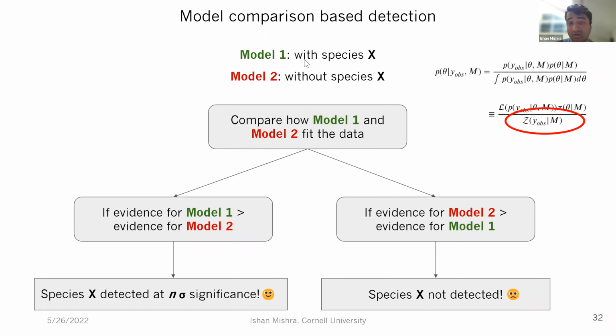If model one, which has all the species, including species X, does better than model two, which does not have species X, then we'll conclude that species X is needed even in the presence of everything else to explain the data. So that translates to some degree of detection significance. On the other hand, if model two does better than model one, that means knocking out species X actually helped, and so it's not really needed. And so we conclude that we don't find any evidence for it. And doing this for all your candidates will lead to acceptance or rejection for them. And you will be left with a subset of species that best explain your data via this methodology.